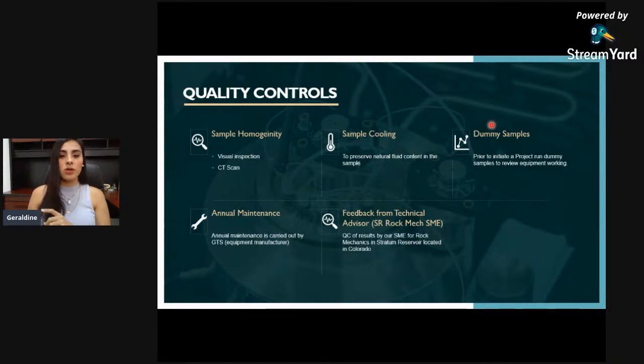Once you have your plugs or samples, another very helpful tool is the CT scanning. With the CT scanning, you will be able to see the inside of your sample, the internal structure. In that way, you can see if you have a very big grain inside, an internal fracture, any heterogeneity that could affect your results or influence your testing in a bad way. In that case, you decide to not run that sample.